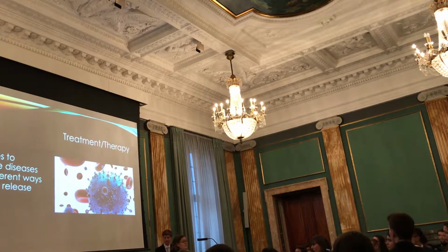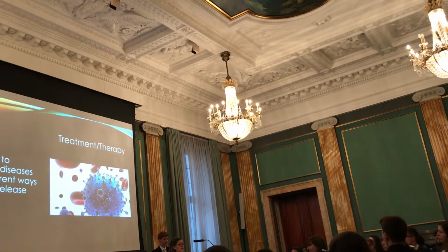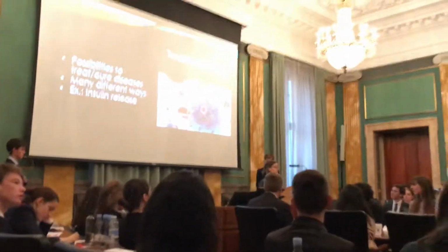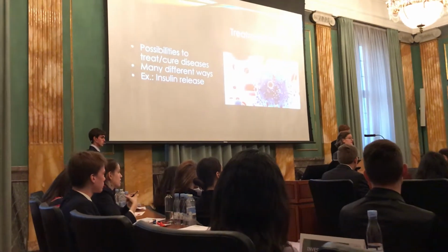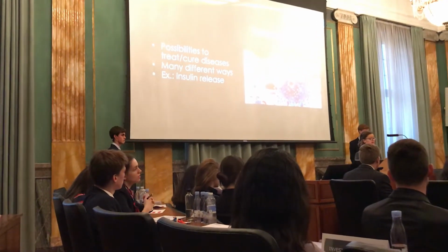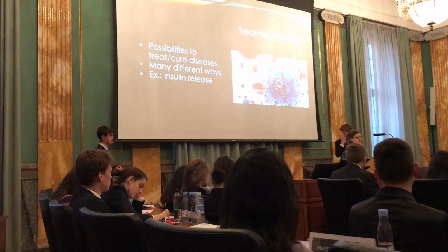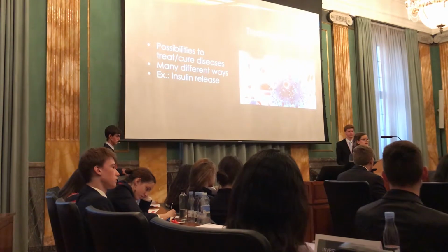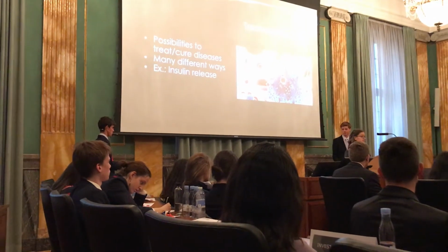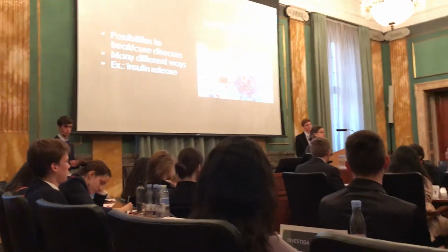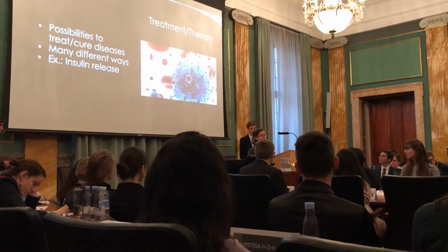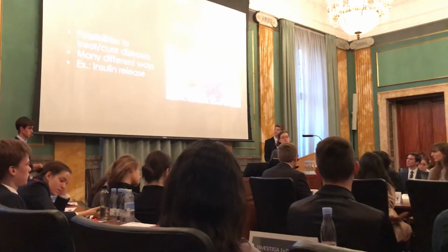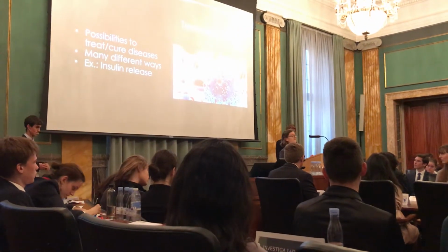An example of this would be the treatment of diabetes by using nanoparticles that work like a sponge to carry insulin. When the glucose level in the blood rises, the nanoparticles release the insulin, and when it drops again, the release stops. In some studies they have done, it has shown that a dose of this can last up to 10 days, whereas with the normal injections we have now, patients have to inject themselves multiple times a day. However, this technique is still in development, as most of the usages of nanoparticles in medicine are.